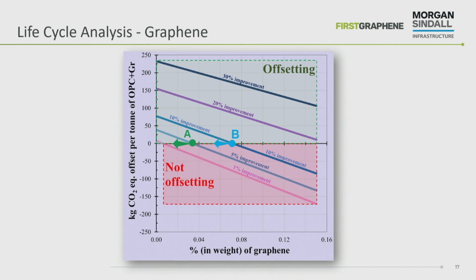So what we want to do is get a percentage improvement so you can reduce the clinker, add more limestone, and is there an offset? You can see on some of these lines here, if you get a 10% improvement or a 20% improvement, how much CO2 per ton you can offset with a specific loading of graphene.